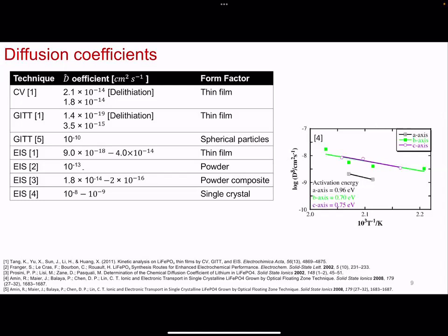So for thin film, they grow it, like it's atomic layer deposition. They grow it onto the electrode. The electrode's there, they pulse in the precursors and it's grown onto the electrode. Now that's different from, let's say, the reference 5 where it's spherical particles or powder composite. There the material is synthesized like in hydrothermal flash, it's preformed and then made into a composite, and then blocking electrodes or a cell is then fabricated. Okay. So all of that was just sort of subsumed under form factor, and I kind of brushed over it. That makes sense. So no, it's not just the electrode.